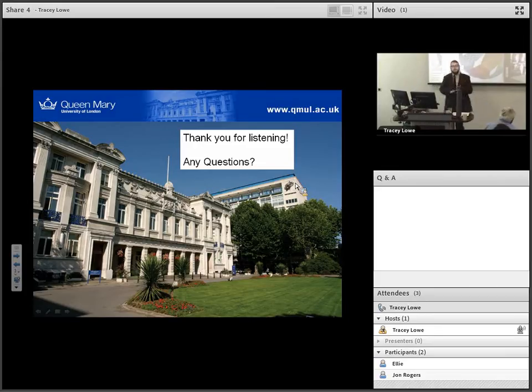The answer to that is not something that we've looked at. It's something which I can't remember which group did it in the mid-90s. They did cycling 3,000 times, and found there was no issue with delamination or anything like that. However, vanadium dioxide is not a particularly hard metal oxide, and part of the reason why in our model we put it on surface 2 is because there is no way it could be an exterior surface. It would weather off of a glazing panel really quickly. It wouldn't last there.